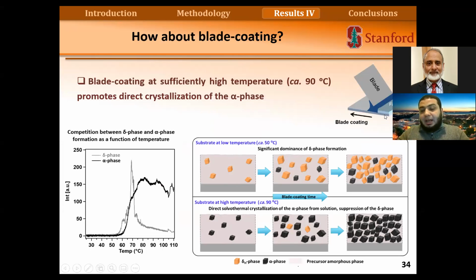So in blade coating also we can apply heat. We can apply heating to the substrate as the coating happens. So we try to see the competition at different temperatures. What we have found, above 70 degrees, the alpha phase becomes more dominant than the delta phase, and below 70 degrees, the delta phase is more dominant. So when we try to do blade coating at 50 degrees, we end up with a film that has both delta phase and alpha phase, and this is not favorable because we still need a second step of annealing.